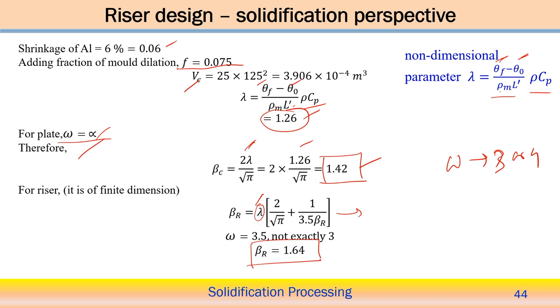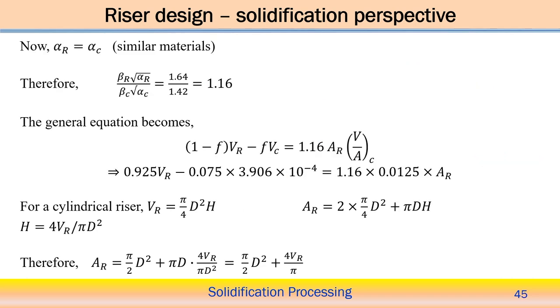Now, once we calculate beta c and beta r, then alpha r, the thermal diffusivity. In this case alpha r and alpha c will be the same, because the thermal diffusivity for both the materials is the same, although the runner and riser are also encrusted in the silica sand.